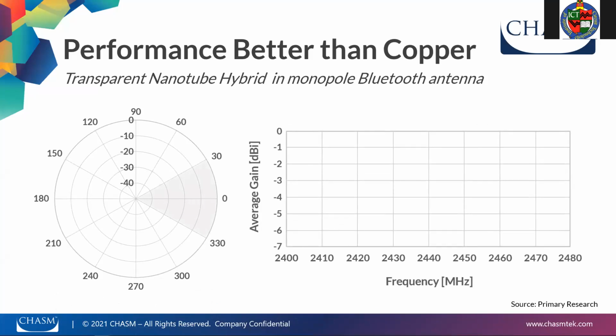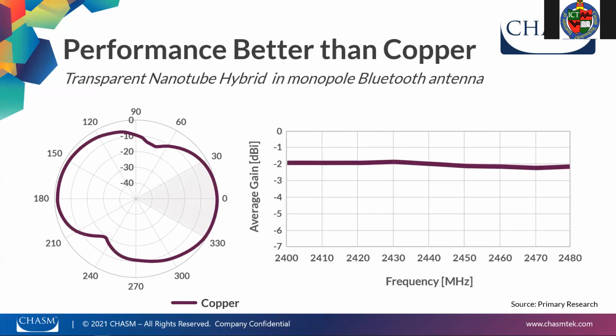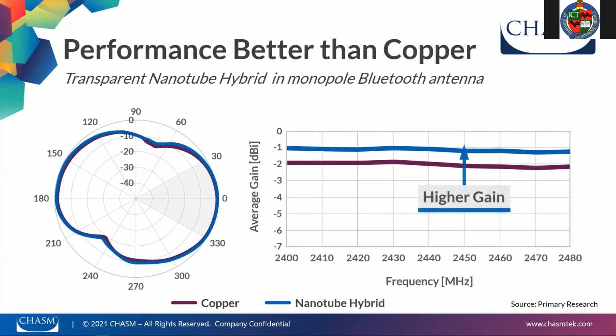For another Bluetooth application, the customer's goal was to add an antenna outside of the enclosure. So they established a baseline using a copper antenna. And you can see in the 360-degree polar view and also the baseline in the frontal view that represents the front of the device, the frequency response there. The nanotube hybrid antenna performed not only equal to the solid copper antenna as it was measured around the full 360 degrees around the antenna itself, but also produced higher gain across the angle representing the front of the intended device. So this really worked well in the customer's application.